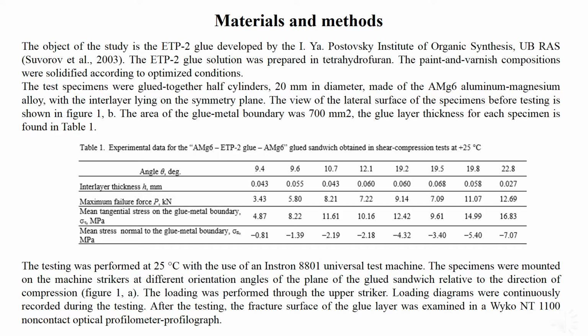The object of the study is the ETP-2 glue. The paint and varnish compositions were solidified according to optimized conditions. The test specimens were half-cylinders made of aluminum-magnesium alloy, glued together with the interlayer lying in the symmetry plane. The glue layer thickness for each specimen is found in Table 1. The testing was performed at 25 degrees with the use of a universal test machine.